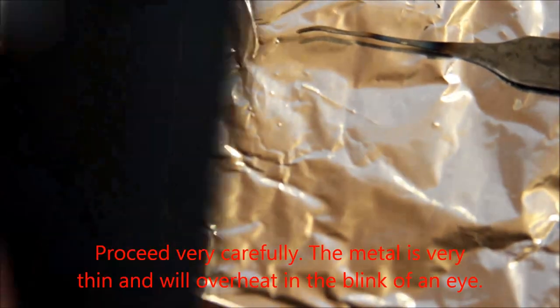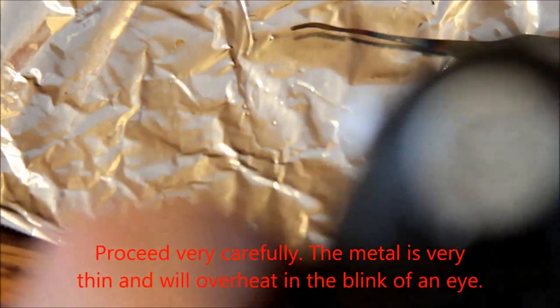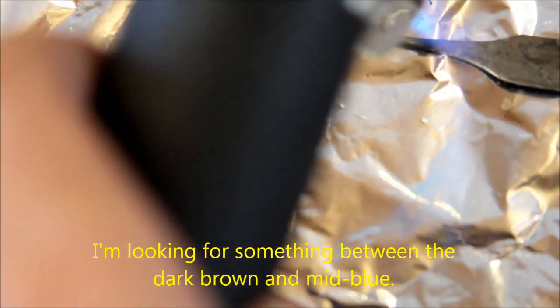But we're basically trying to get that rainbow sort of color through there. Note that the oxidation products will not show up while the flame is on the metal, so you have to keep moving it on and off or you will overheat it and burn it.